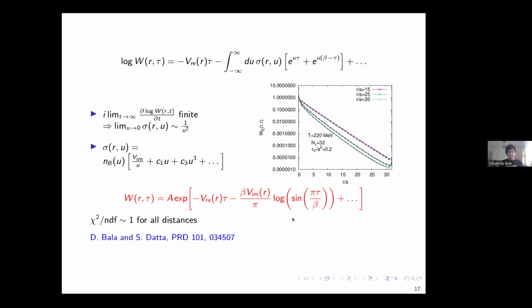Okay. So once we have that, we can just fit the lattice data to extract the real and imaginary part of the potential. Earlier it was not known what the possible form of the Wilson loop should be at finite temperature. It was only known at zero temperature, but for finite temperature, we derived that this has to be the form, this extra functional form. Now this fits the lattice data very well with a very nice chi-square per degrees of freedom. Now I can show you some measurement of this real part and imaginary part by fitting the lattice data.